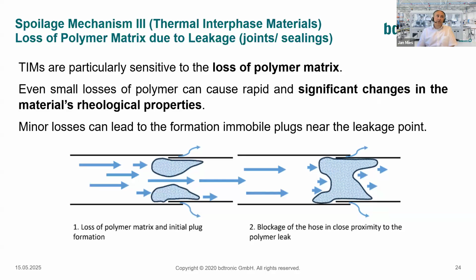On the next slide, I want to talk a little bit more about the non-self-leveling materials, especially the thermal interface materials that Till already presented. Those thermal interface materials are particularly sensitive to the loss of polymer matrix. Remember, I said that the filler level of those materials goes up to roughly 80% or even more of filler, which is a solid. So a loss of a tiny bit of polymer matrix could jeopardize the flowability and drastically influence the rheological properties of such materials. A complete showstopper is leakage in your hosing and piping, where joints and sealing elements are not completely tight towards the transport of the polymer matrix.